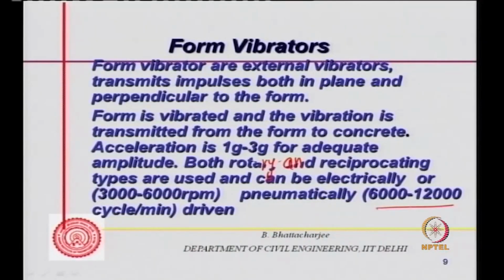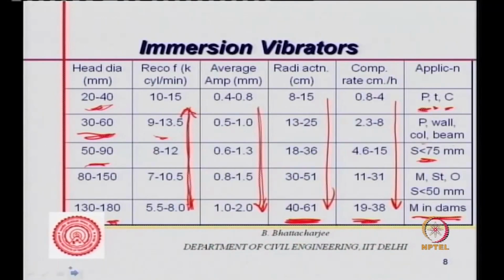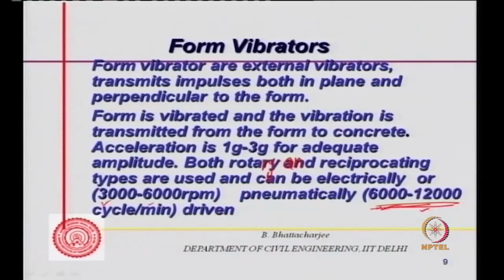And you can see the RPM. So if you can see the RPM, kilocycles per minute is 6 to 12 kilocycles. There is 3 to 6 kilocycles per minute. So if you look at the earlier cases, this is relatively on the higher side. For the larger needles, we use lower frequencies. If you go back to the previous one, you can see that the 10 to 15, the first smaller, thinner ones were using high frequencies. So this is somewhere in between. So that's what it is.